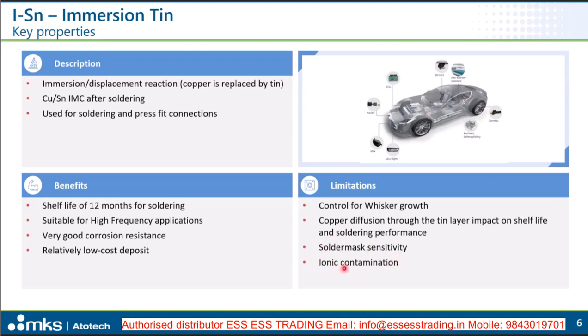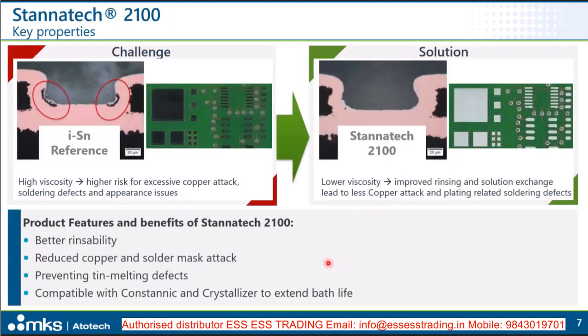Another risk is that we create a high ionic contamination. It's also related to the solder mask compatibility, because again, if the solder mask is poorly applied, if it's not well cured, it may soak in the immersion tin chemistry, and this will later on create high ionic contamination values. But we will talk about this later on as well.